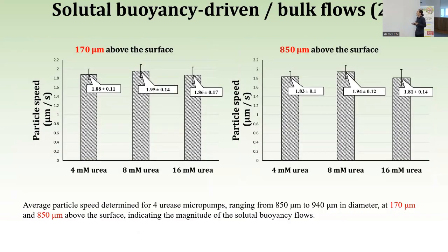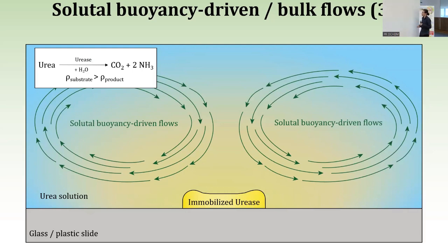This particle tracking also helps us with determining the flow speeds. As you can see, the values of these speeds were not dependent on the substrate concentration, and they were pretty similar in both cases, at 170 and 850 microns height above. So this is a schematic explanation of what I just explained.